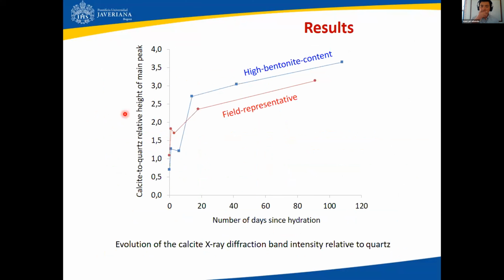The same data, we can plot it in this chart, and what you see here on the x-axis is the number of days, up to 3 months roughly, since hydration, and on the y-axis you see a relative height of the main peak from the X-ray diffraction patterns when we compare calcite divided by quartz, because quartz was basically constant during the testing. So except for this small decreasing trend that, to be honest, we haven't explained, we see a general trend of increasing calcite peak intensity. That intensity of the peak typically reflects either crystallinity or content. So we believe, anyway, that carbonation is taking place.